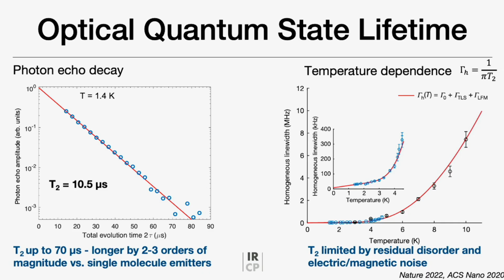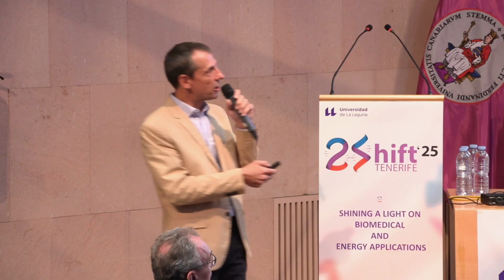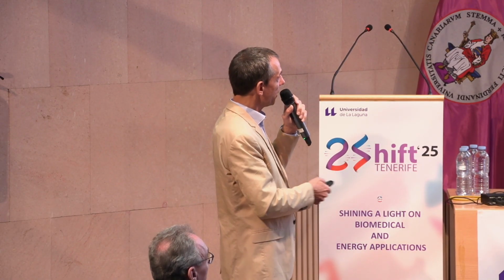This is quite interesting in the context of these molecular emitters, because first of all, we were quite surprised to see any photon echo in the system. The general consensus was that these materials were not very useful for quantum applications. But in fact, you can measure something. It's 10 microseconds. Actually, it can be up to 70 microseconds. In some samples, we could see a long component of the echo decay corresponding to 70 microseconds.